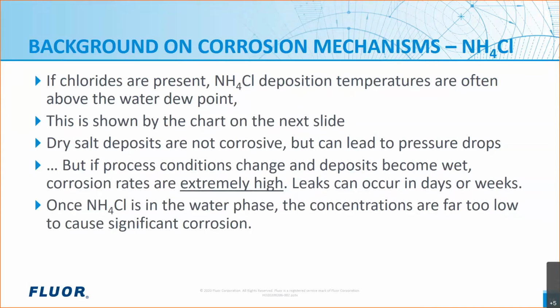Now, for units that are having ammonium chloride salts, sometimes they occur upstream of the water injection point, say in that last shell and tube exchanger, the feed effluent exchanger or reactor effluent stripper feed exchanger. If you're forming the salts and they're dry, they're not going to be corrosive because it's still an aqueous corrosion mechanism. But the dry salts can lead to pressure drops, and some units have to do an intermittent water wash every month or so to wash away the deposits just to get rid of the pressure drops.